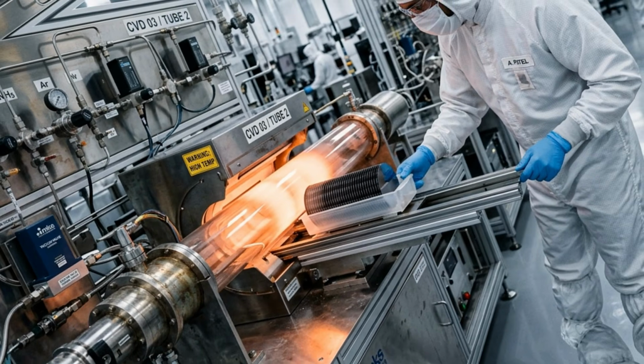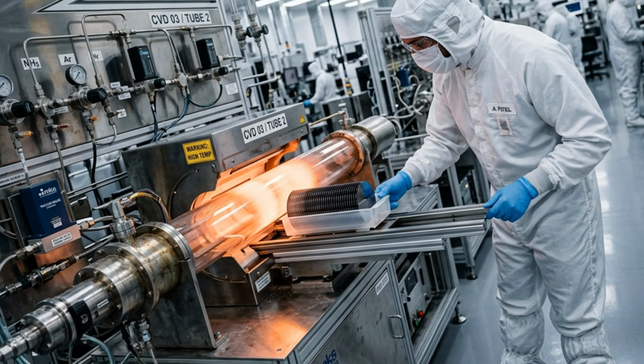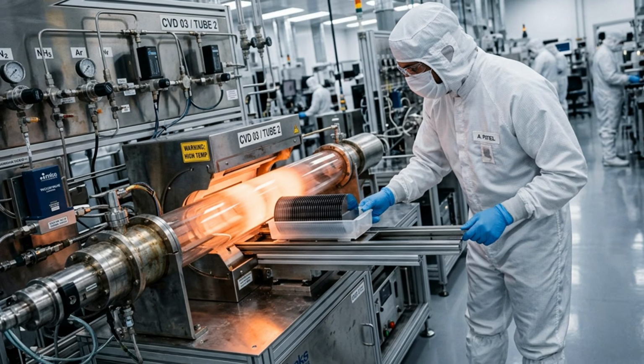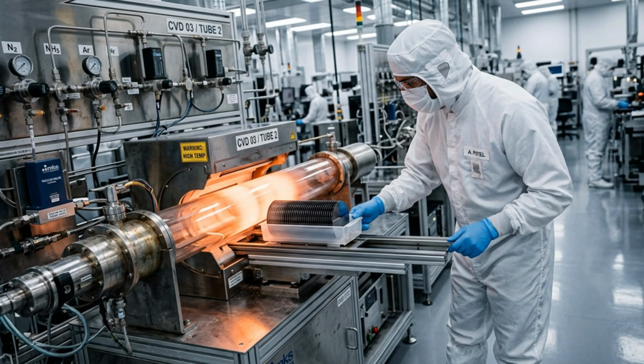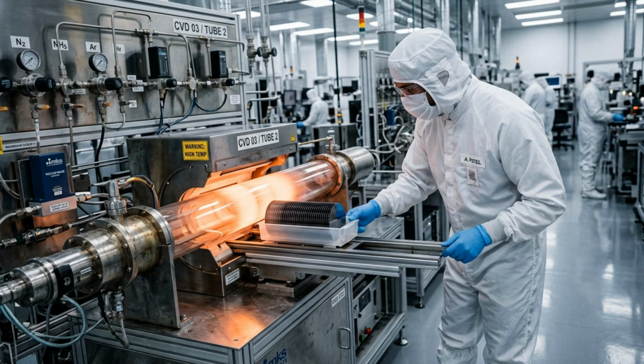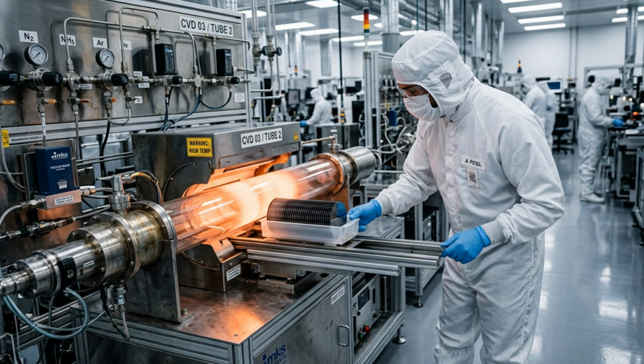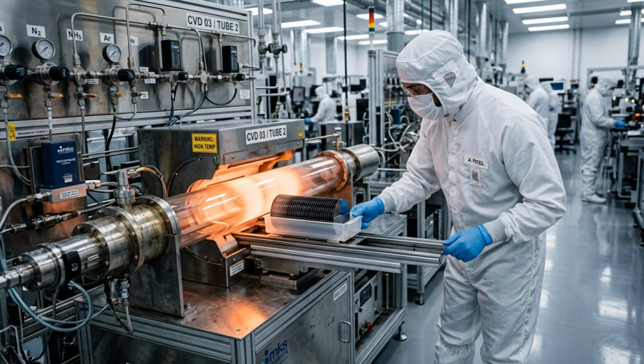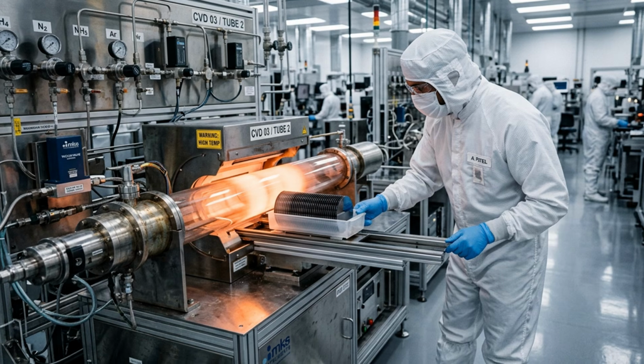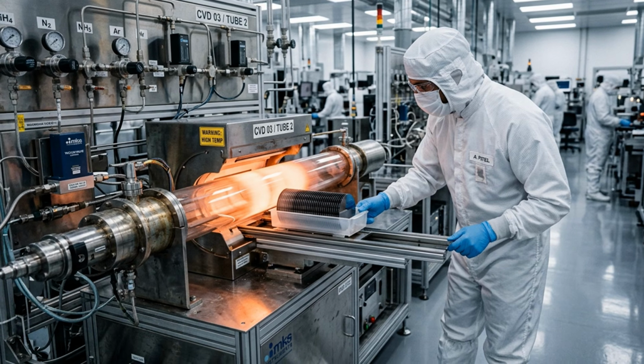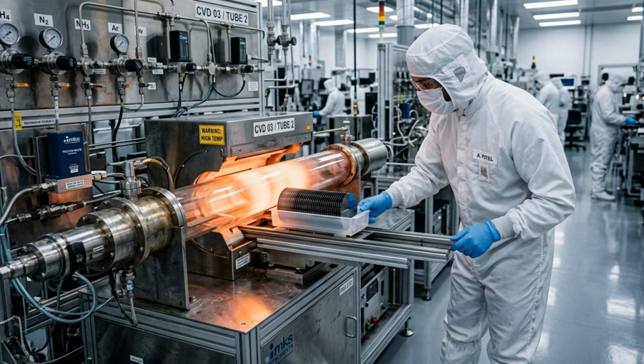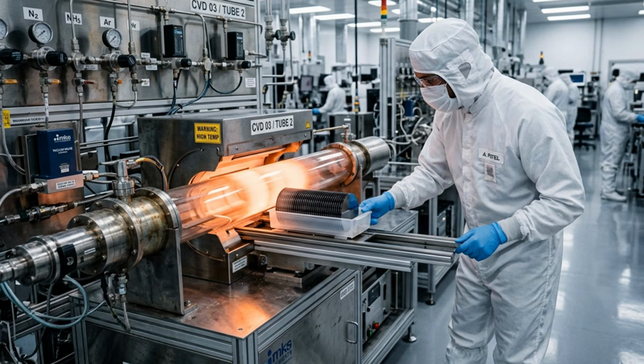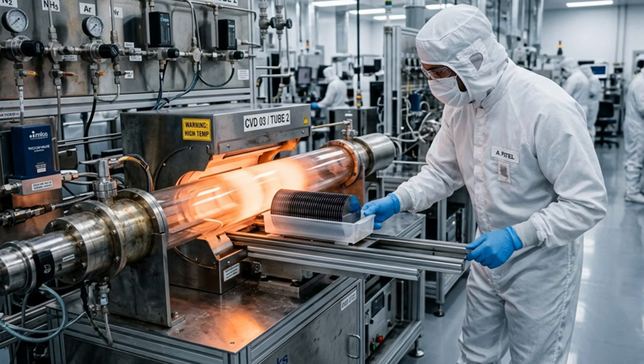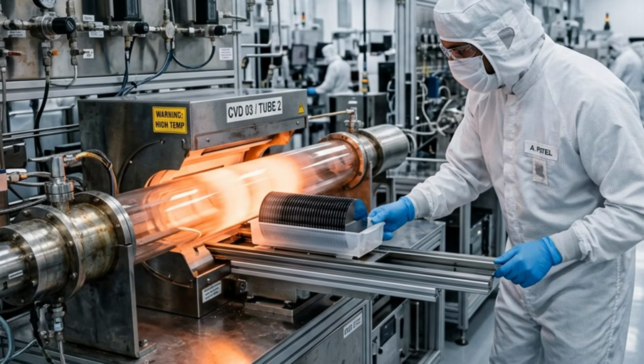Each stage must work perfectly. A mistake at layer 50 doesn't just affect layer 50. It cascades down through the remaining 100 layers, potentially making the entire chip worthless. This is why yield, the percentage of working chips produced from a single wafer, is one of the most closely guarded metrics in the semiconductor industry. For the most advanced chips, early yield rates can sometimes be below 50%. Every failed chip represents thousands of dollars of lost material, energy, and machine time.